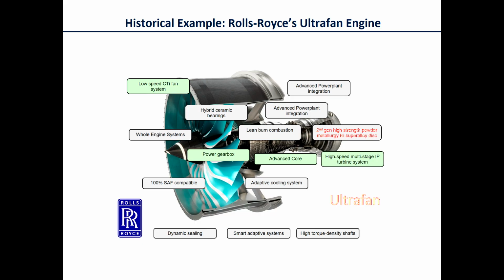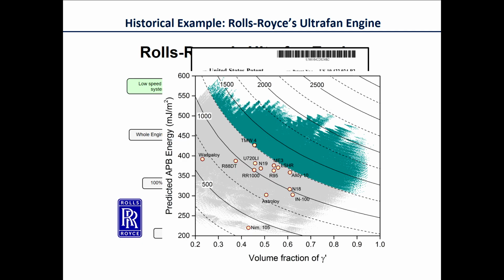And at the back here, you can see a new second generation high strength powdered metallurgy disc that was designed by my group, and again, patented, as these things have to be. And the key point here actually was to try to map the fraction of this gamma prime strengthening phase, and also this APB energy here, which we calculated using electronic structure calculation methods. It turns out that when you look at the theory here, you have these isobars, and we want to be working in the top right-hand corner of this diagram.